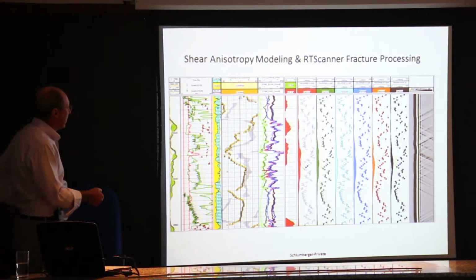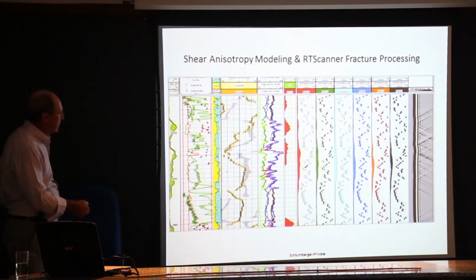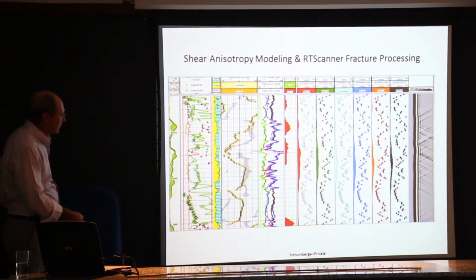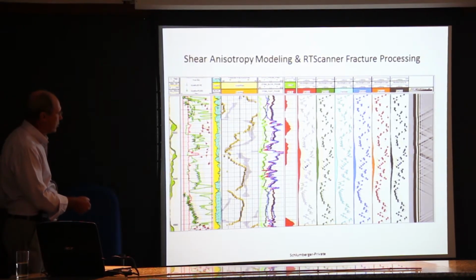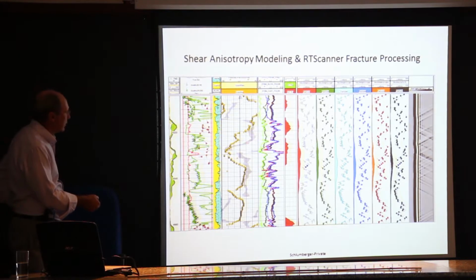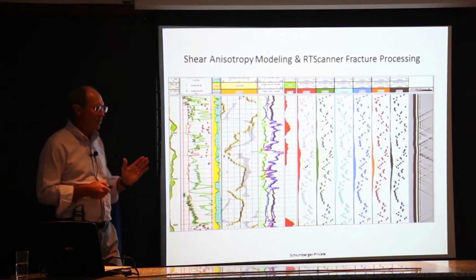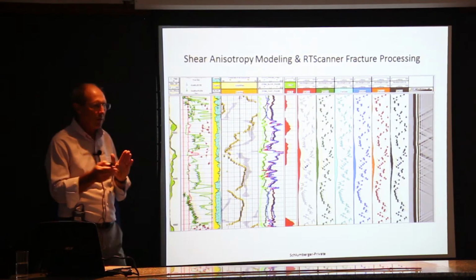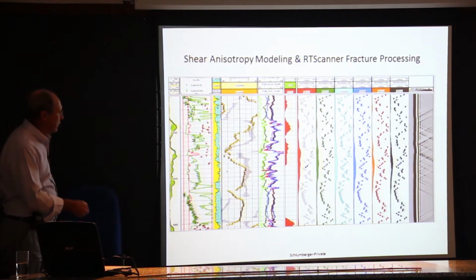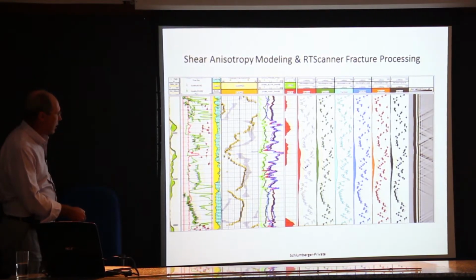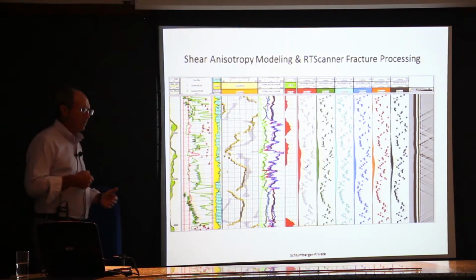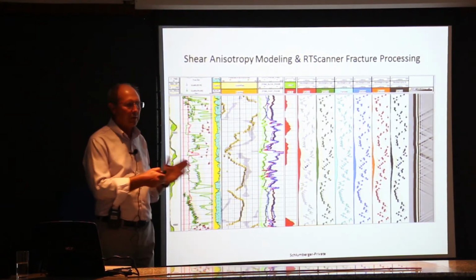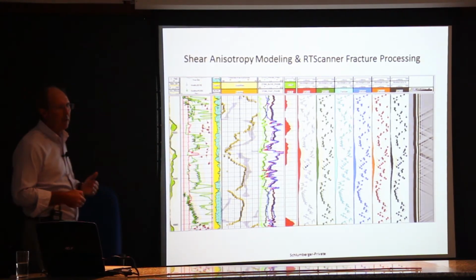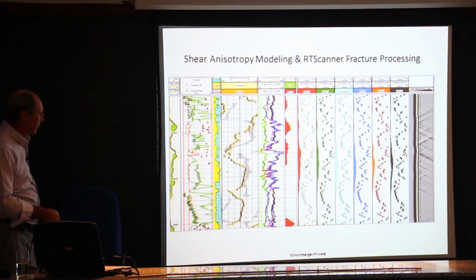What we have here in the dots is the orientation of the fractures as we see on the image log, and then the shaded area is the orientation of the fast shear based on the four-component rotation. And where you see good agreement is usually where you have these natural fractures. Where you don't have the fractures, you get this ambiguity. You don't have really much signal in terms of fast and slow shear to really resolve the angle of the downhole stress or the fractures. So you'll often get disagreement here.